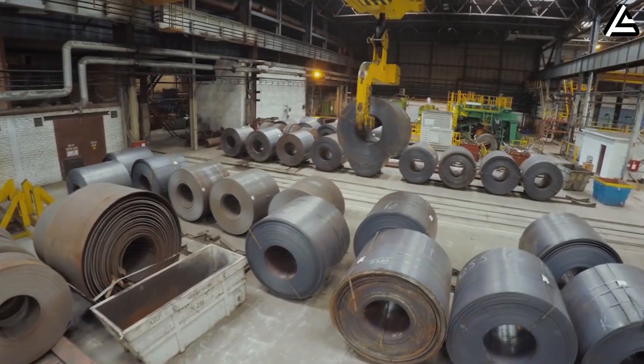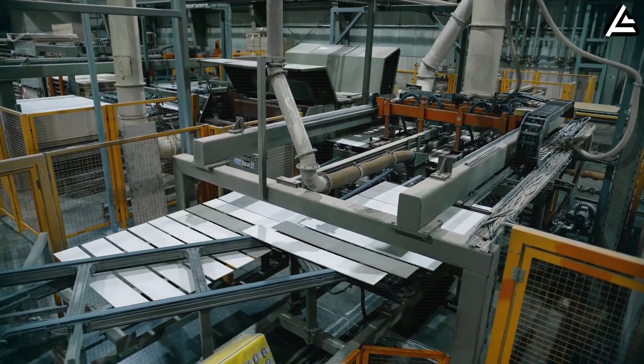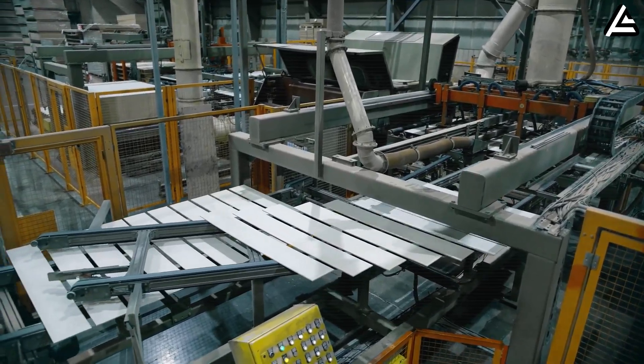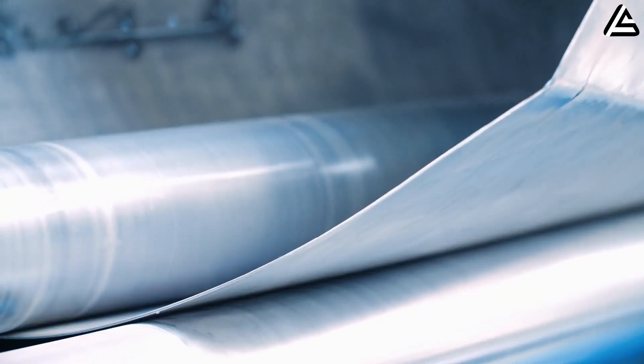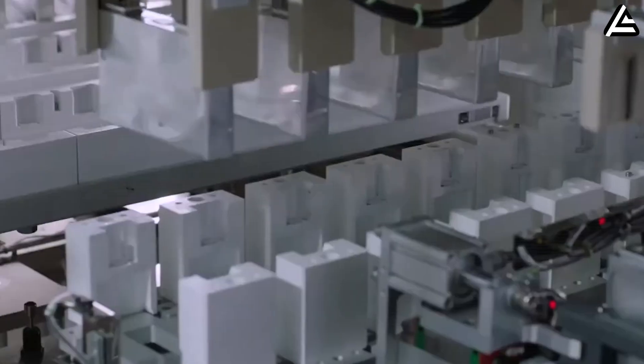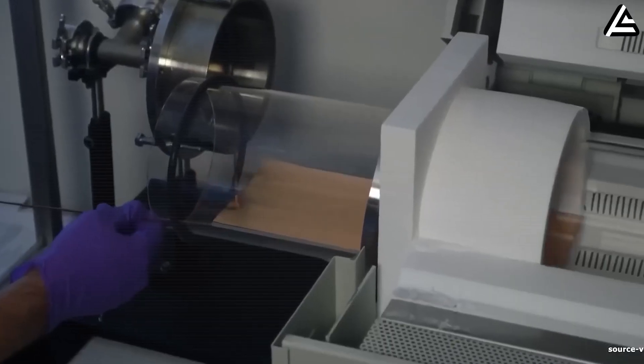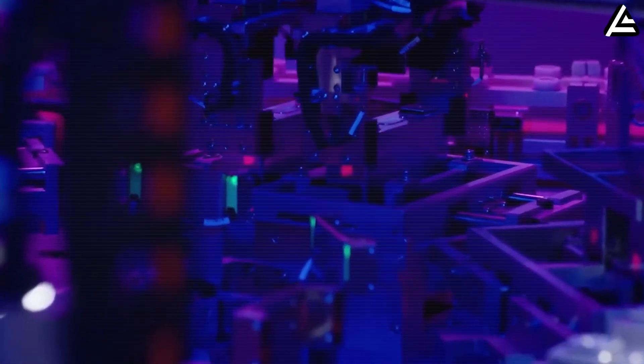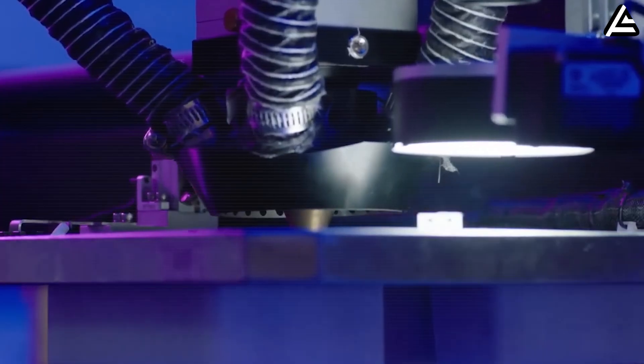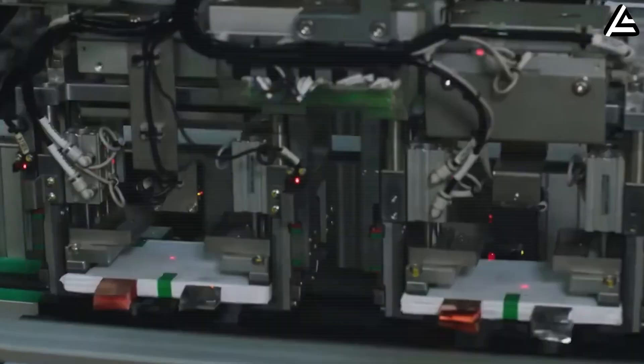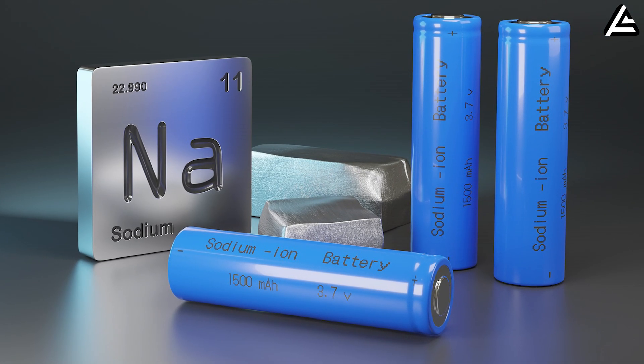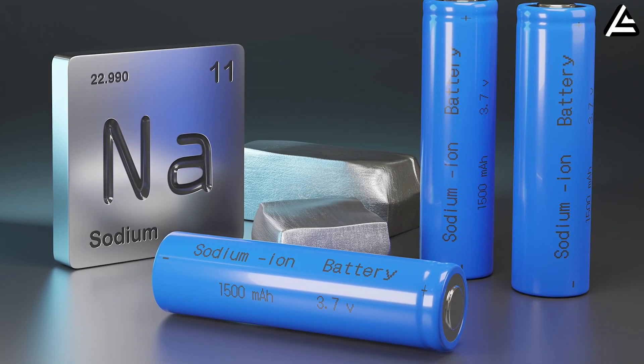Material costs also tell the story. Aluminum metal is cheap at roughly $2,200 per ton, but the extra processing needed to fabricate aluminum-ion electrodes, combined with higher rejection rates in lab-scale prototypes, often 20 to 30 percent, drives the effective cost per kilowatt-hour well above $200 per kilowatt-hour, far above Tesla's target for mainstream EVs. In contrast, sodium solid-state designs could plausibly hit $120 to $140 per kilowatt-hour at scale, making them attractive for lower-cost EVs and energy storage applications.